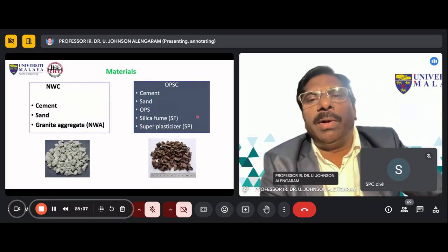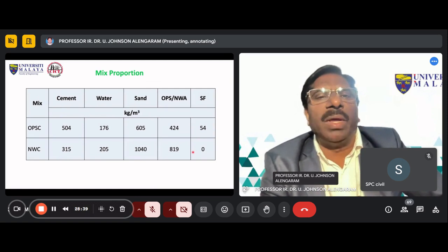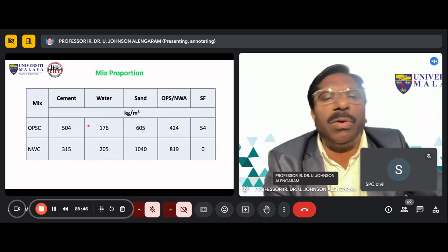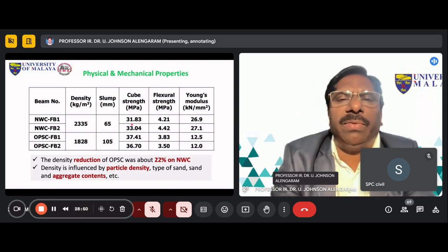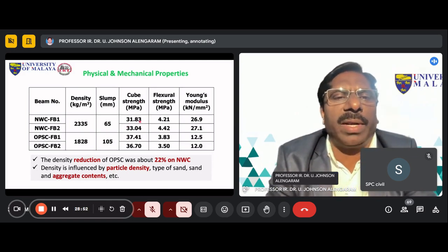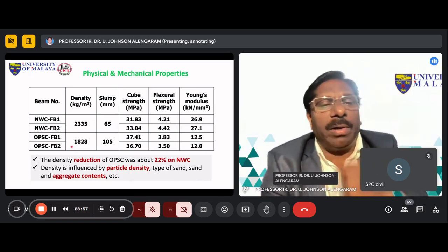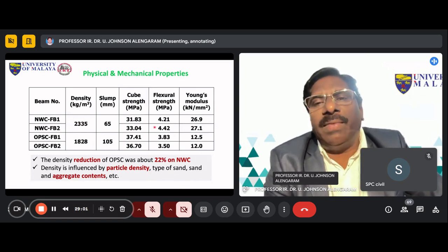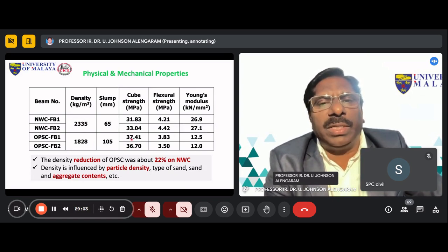So what we did was we used the normal concrete. We also developed oil palm shell concrete, and we utilized more cement. Normally in a lightweight concrete, we need to use more cement, that's expected, and we produced concrete of grade 30, around 30. This is normal weight concrete, density of 2300, whereas the density of our lightweight concrete is 1800, almost 22% reduction on normal weight concrete. Nevertheless, the strength was almost 33 here, 36, it's almost very close.